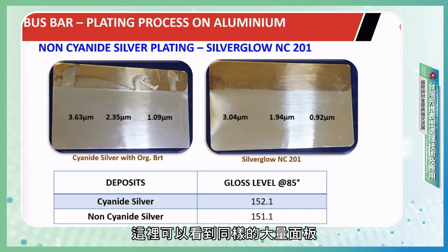You can see that for the same Hull cell panels, we have checked the gloss meter at 85 degree angle, and we see more or less similar light reflection, so cyanide and non-cyanide are in the same range. From a brightness point of view, I would say it is comparable, and in some cases, by altering the brightener part, we can even make it a little better.